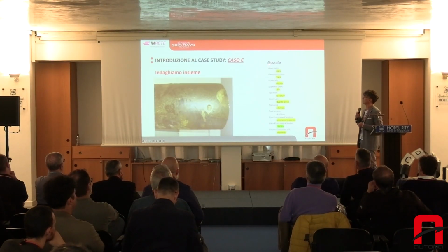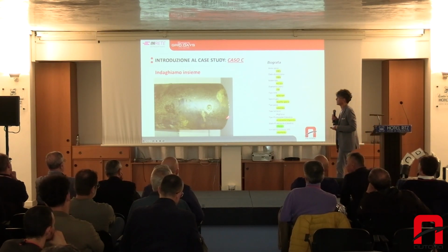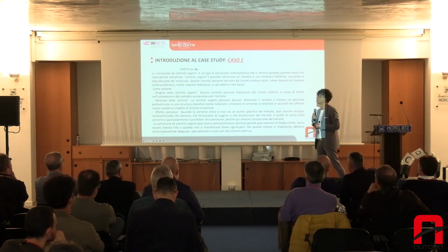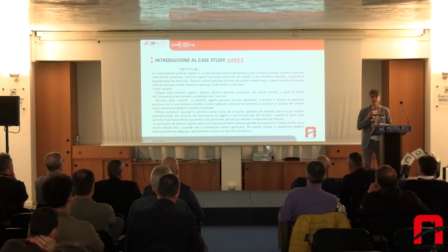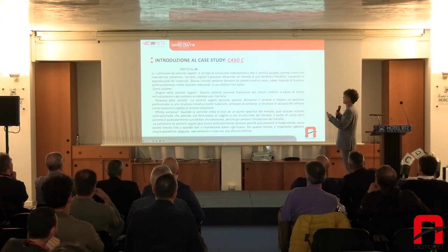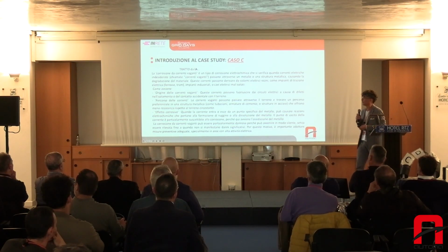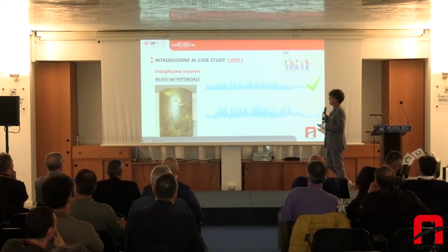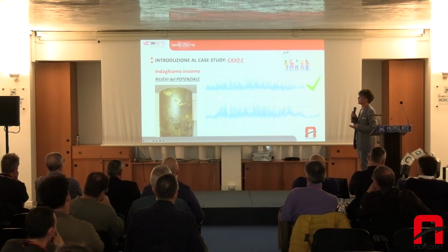Third case, this pipe was laid in 2003 and no longer used in 2008. There too there was a variability because of interferences, and as a matter of fact this is a type of corrosion because of stray currents. From the image, the artificial intelligence was not capable of saying that it was corrosion from stray currents, and therefore I interrogated the artificial intelligence once again, asking if it knew what stray currents were, and so on.